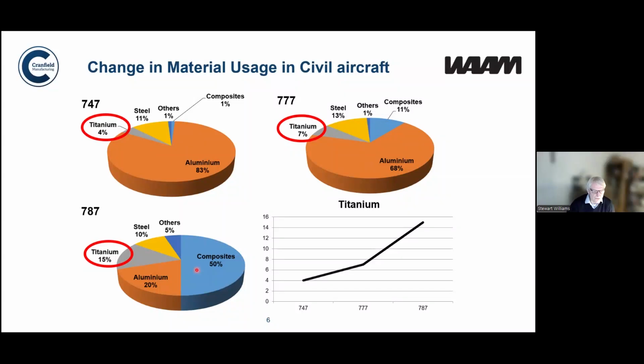And there's an issue that aluminium is incompatible with carbon fibre composite due to corrosion. So they couldn't use the aluminium where it was in contact with the composites. So our titanium amount in the aircraft had gone from 4% to 15%. And in a typical 787 at this time, in the early 2000s, there were roughly $20 million of forgings on the 787. And given that the cost of material was round about, or still is round about, $50 a kilo, if you're machining most of it away, this is a very expensive method.